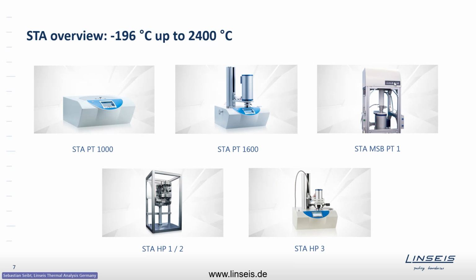On the right side, on the top line, you see a very specific instrument, the so-called magnetic suspension balance, which is a contact-free sample chamber. That means the sensor head is not connected by a rod to the balance unit. In that case, there is a magnetic coupling. You have two magnets that keep the sample holder in an elevated state all the time. So you have an enclosed furnace with a very defined volume. This is designed for very corrosive atmospheres, for very reactive samples, for very critical conditions. It's a very special version. On the lower line, you see one other special version, the so-called pressure balance. We have a floor-mounted STA high pressure 1 and 2 system.